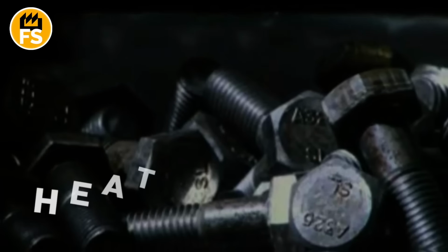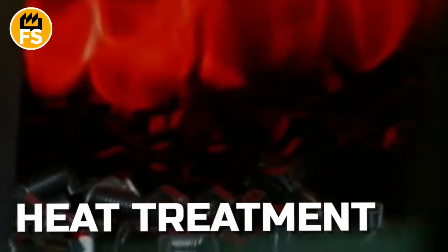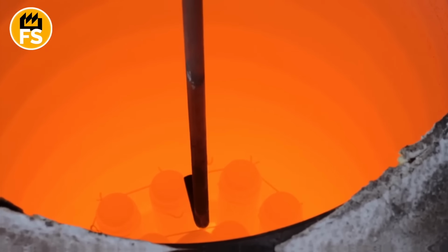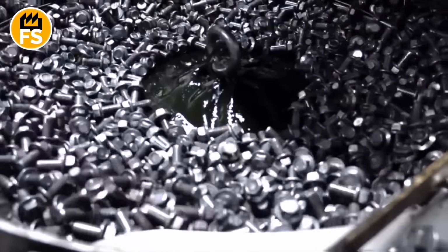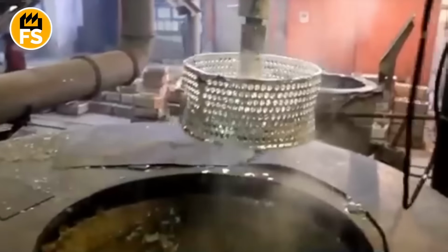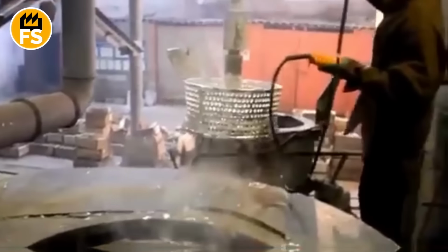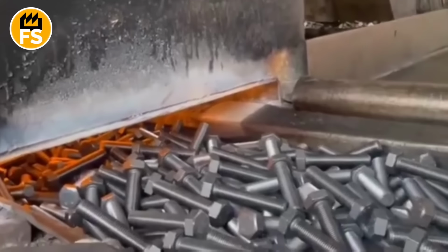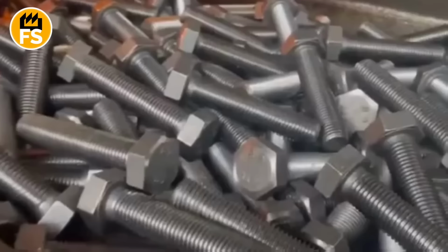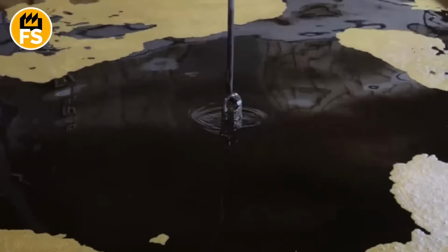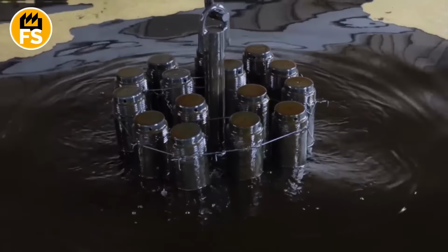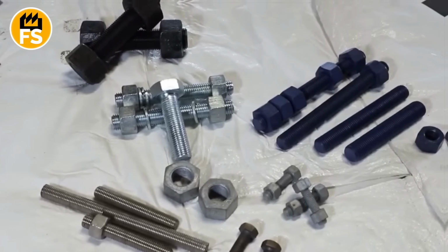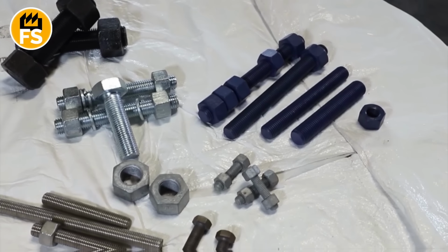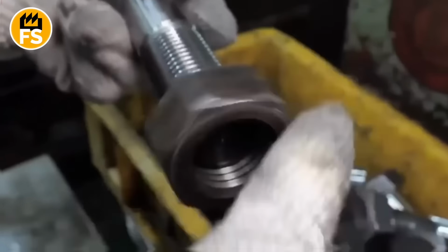Next stage, heat treatment. Bolts go into a furnace and get heated to 1550 degrees Fahrenheit, then rapidly cooled in an oil bath. This is called quenching. The steel becomes exceptionally hard, but brittle. So right after quenching comes tempering. The bolts get heated again, but this time to 600 degrees and fully cooled. This removes the brittleness while keeping the hardness. The result? Perfect balance. The bolt's hard on the outside, but tough enough inside that it won't crack under impact loading.